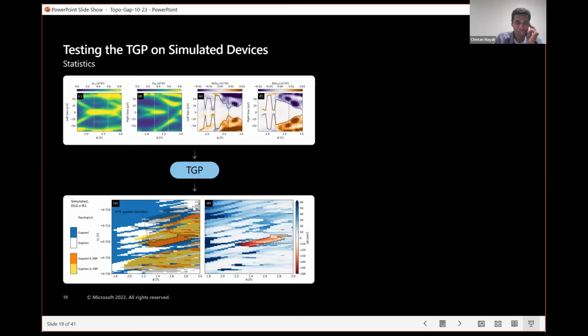This hatched region here, since it's a simulation, we actually know where the scattering topological invariant is equal to -1. And so this whole region here has topological invariant equals -1. Okay. And so what we're doing here is we're comparing the result of calculating the topological invariant, which we can only do in a simulation, to the output of a transport measurement, which we can do both in simulation and experiment.